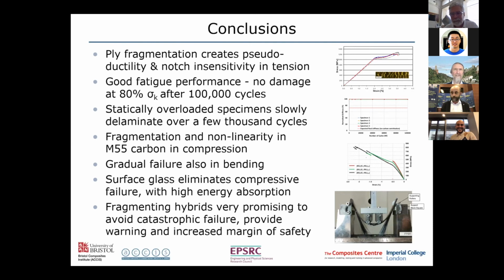So what I can say is that you're absolutely right about the fracture toughness being really important, and I didn't mention it, but the whole behavior of these materials depends on what the mode 2 delamination fracture toughness is. So if you have a tougher material, then the critical ply thickness to get this sort of response becomes higher because you need to get a certain amount of delamination, but not too much. So the fracture toughness does come into play.